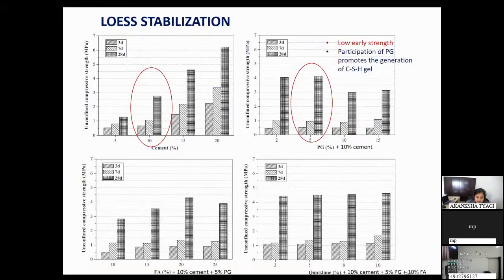Now they also studied what happens when you add fly ash, with 10% cement and 5% phosphogypsum. In this study, as you see on this slide, bottom left, the strengths are higher compared to when you are only using cement. But when you are using 25% of fly ash, the strength has reduced. But if you see these strengths, these are higher than here. And this strength is also higher than when you were only using cement or only using phosphogypsum and cement.